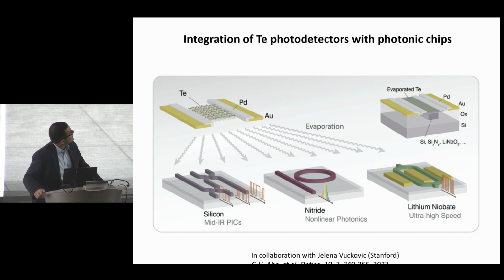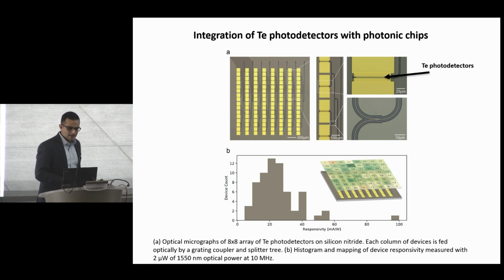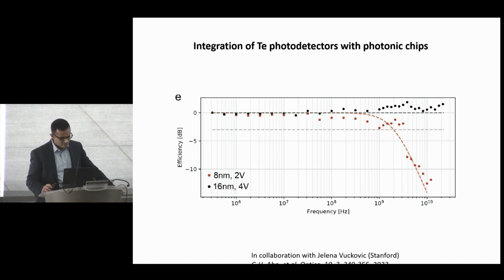Tellurium photodetectors can be readily integrated with photonic chips. We collaborated with Yelena's group at Stanford, and we grabbed some of their photonic structures, the waveguides based on lithium niobate, nitride, and also SOI. We integrated our tellurium detectors, and it works, not surprisingly. And so here are some optical images, and here you're looking at an 8 by 8 array of detectors used on silicon nitride waveguides. These devices are also fast, and we were able to operate them up to 10 gigahertz, and without significant droop in the efficiency. So we have fast detectors.